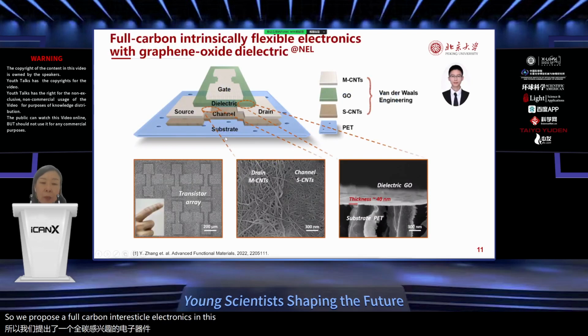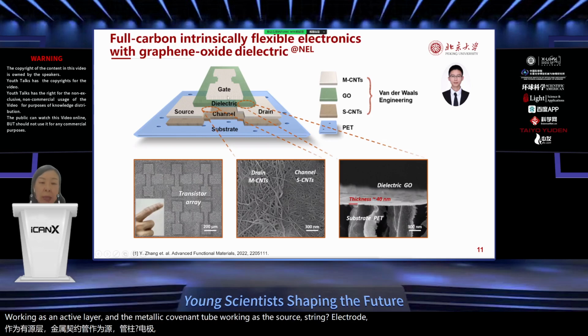In this device, we use semiconducting carbon nanotubes working as an active layer, and the metallic carbon nanotubes working as the source, drain electrode, and also the gate electrode. For the dielectric, the very good choice actually is the graphene oxide, because the channel, the electrodes, and also the gate are all carbon-based. If we choose graphene oxide as a dielectric, it is also carbon-based, so the interfaces between them are very preferred. You can see if you use just carbon nanotubes and the graphene oxide, we can get kind of an integration of the transistor array like this.